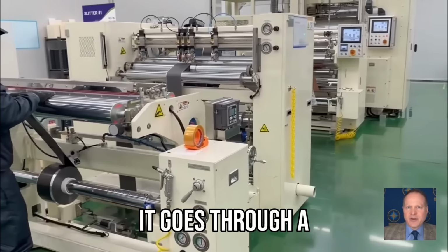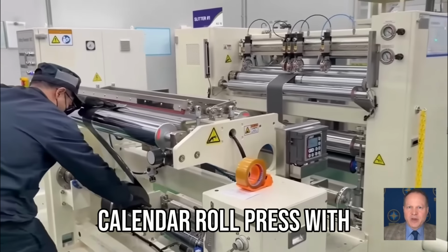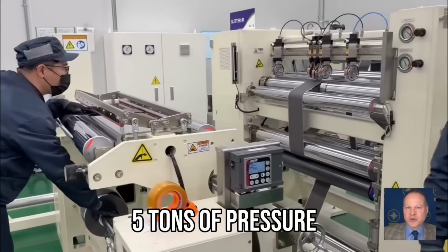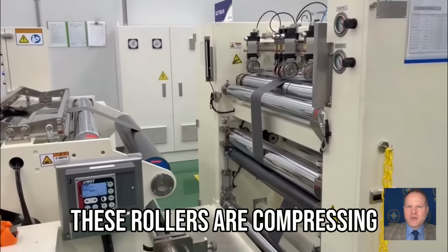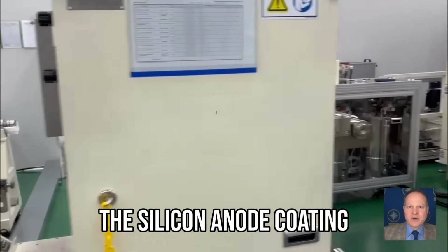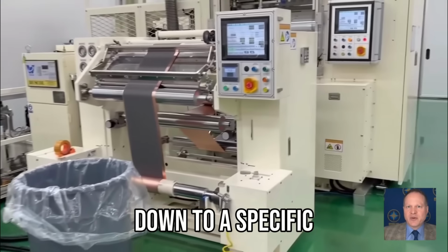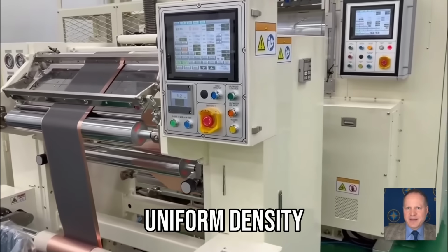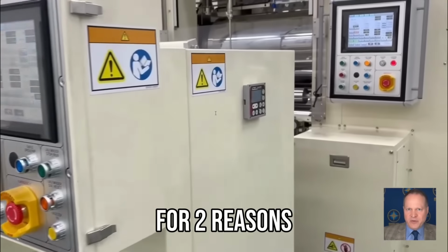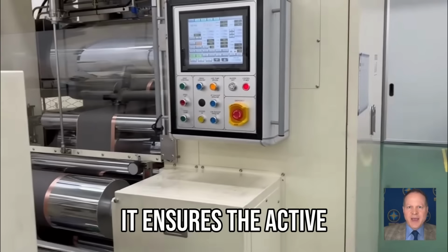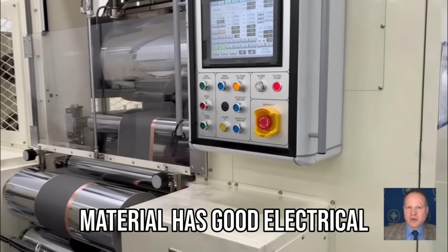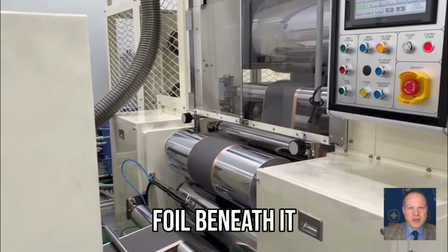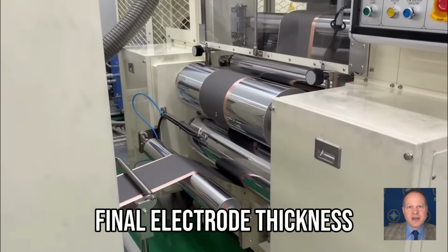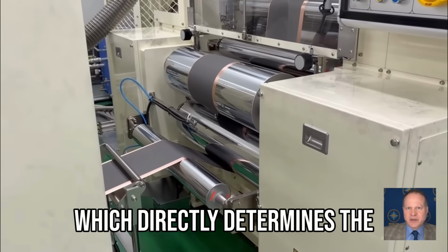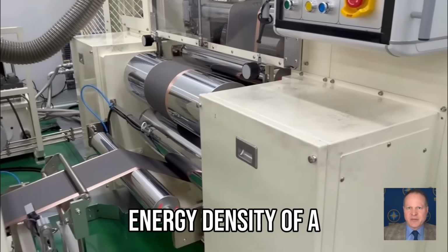After the oven, it goes through a calendar roll press with 5 tons of pressure per centimeter. These rollers are compressing the silicon anode coating down to a specific uniform density. This step is critical for 2 reasons. It ensures the active material has good electrical contact with the metal foil beneath it, and it sets the final electrode thickness, which directly determines the energy density of a finished cell.